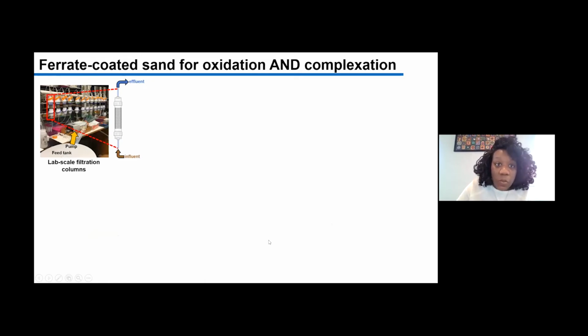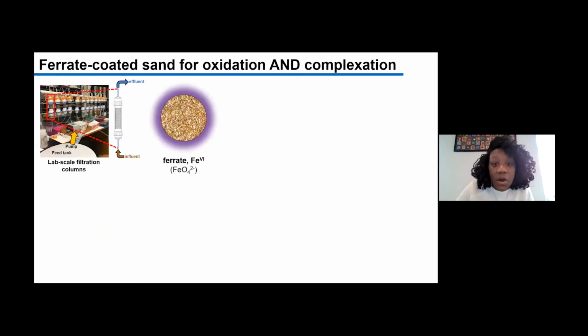So what my group is doing, in recognizing that, to use ferrate, it might not be the best approach to just add silica gels into a stormwater system, is building a ferrate coated sand composite material. So the purple here represents the ferrate, and then it's coated on this grain of sand. The sand serves two purposes. It's a structural support for the ferrate coating, and sand is primarily made of silica. So the silica will then also serve to help stabilize the reactivity of the ferrate coating.